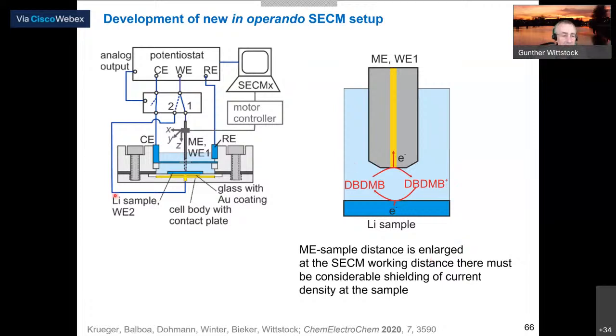And then we constructed that measurement cell. This is a cross-section of the SECM cell. The microelectrode is here. Our lithium metal sample is here. There's a special way of contacting it from the bottom, but that's not the main point. The main point is this here. This is a combined auxiliary electrode for the microelectrode, but also a counter electrode to charge and discharge this metal electrode. And in order to do that, we have a potentiostat, and that potentiostat can switch the role of the working electrode between the microelectrode and the lithium metal electrode.